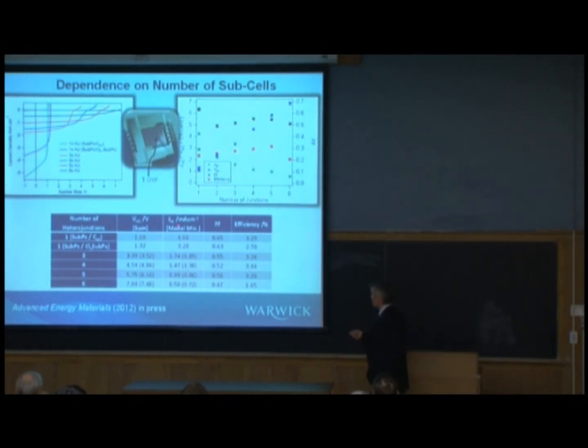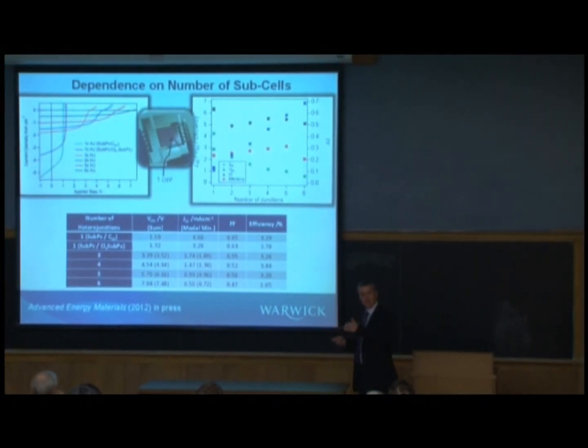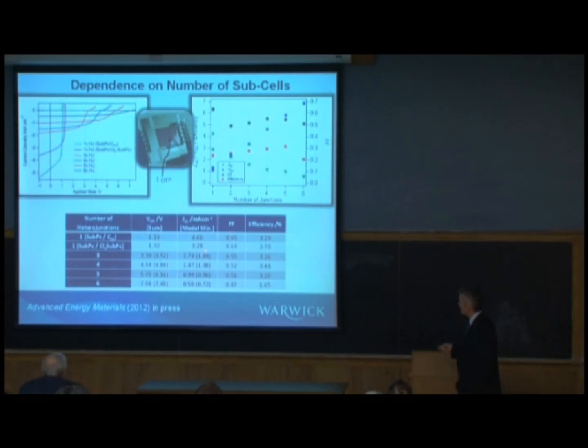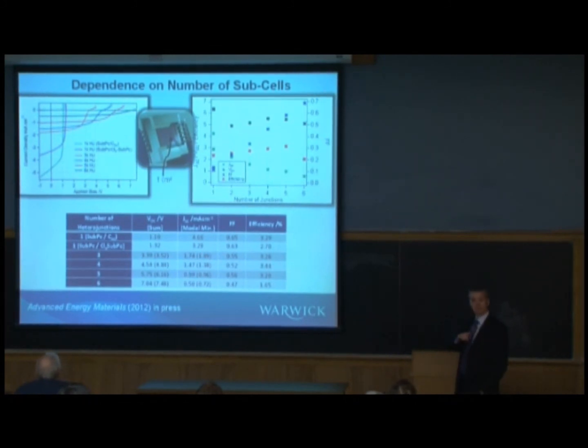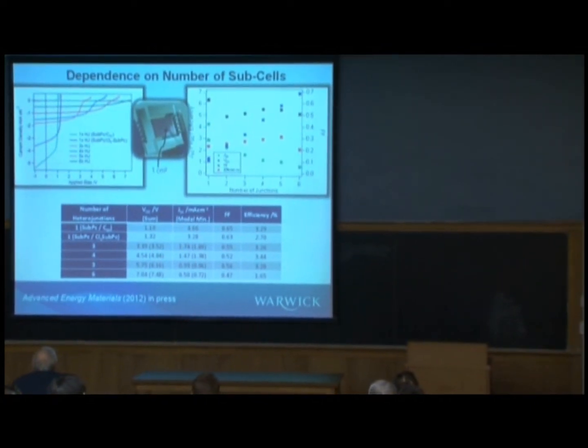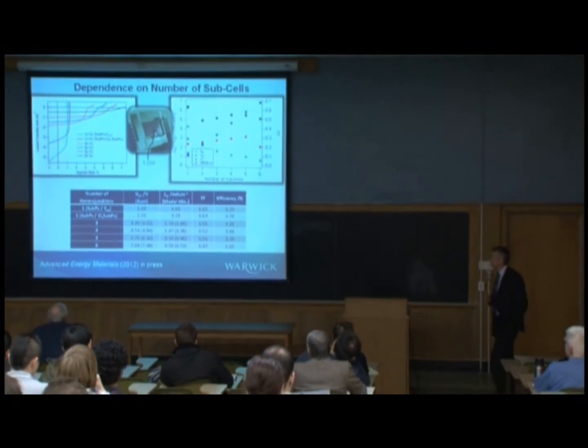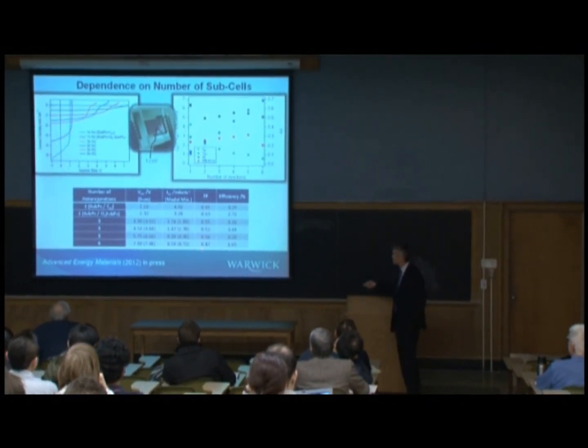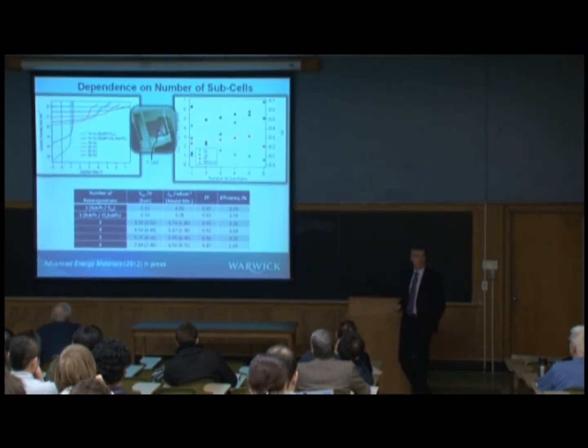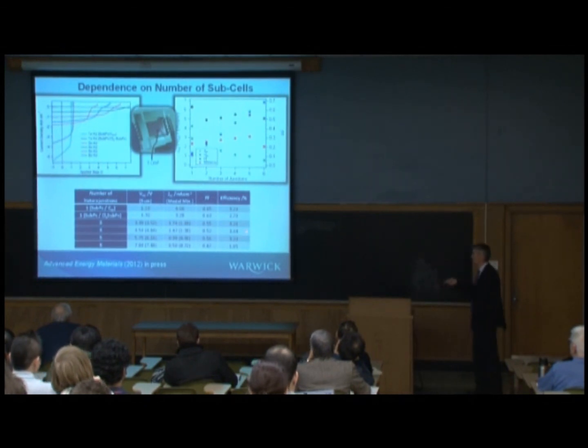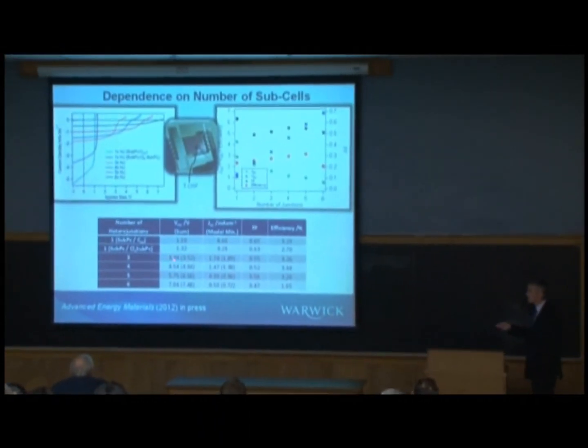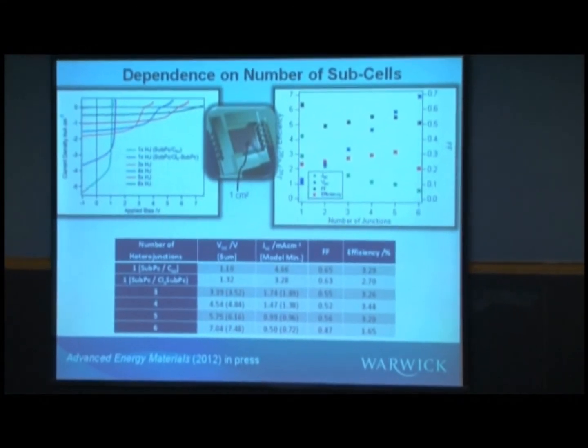The currents extracted start to go down as the device gets more and more complicated, and we now need to work on that to improve those currents. But again, the numbers in brackets are the modeled minimum currents I showed you in the previous slide. So again, the difference between these currents is really not very significant. So again, it validates the modeling that you have to do to optimize the device. Pretty good fill factors for such a complicated device, around 0.5. And the efficiency is pretty good, remembering that the currents are quite low. It's the voltage we're trying to enhance.